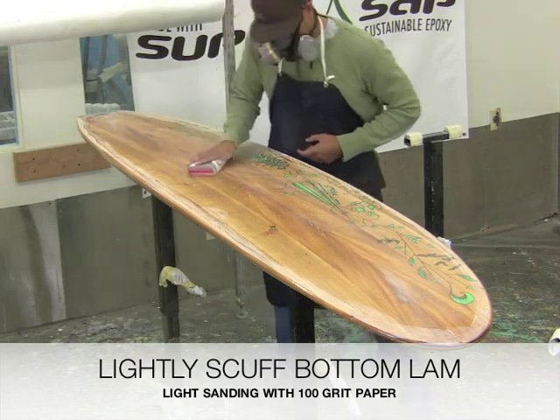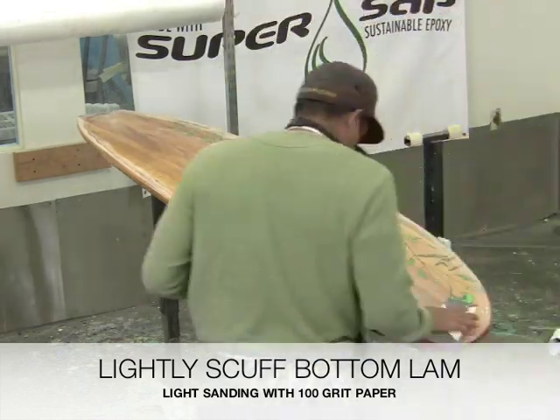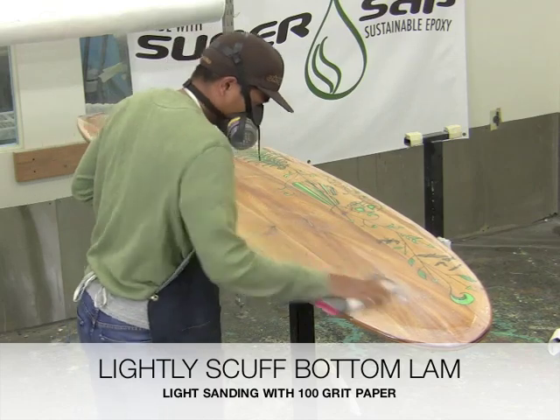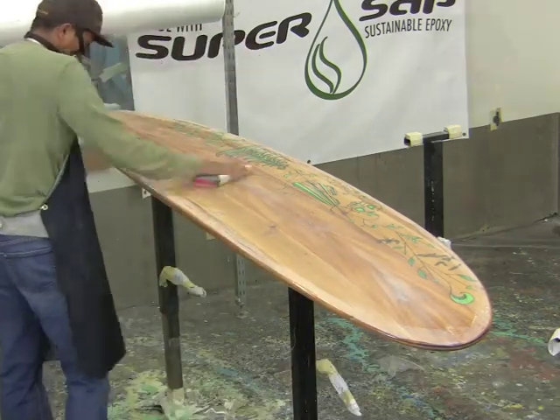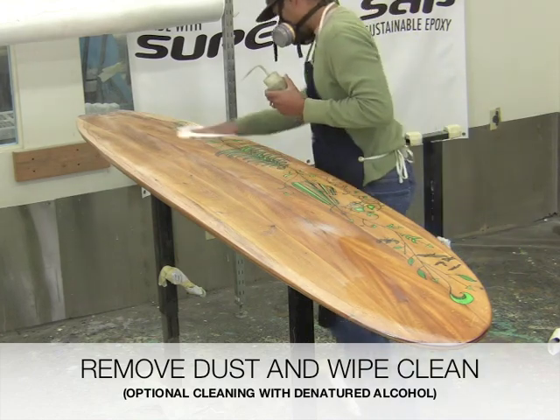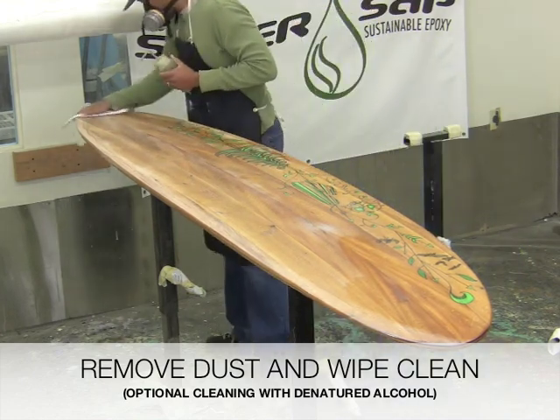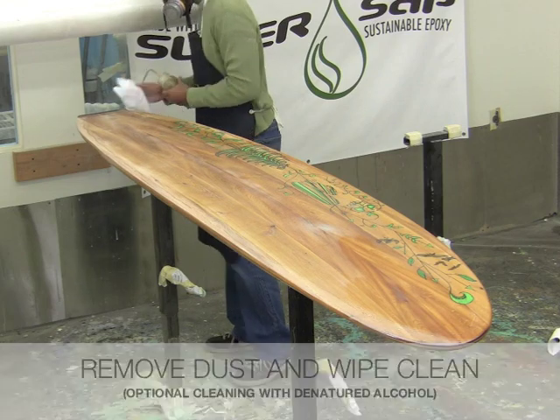Lightly scuff the cured bottom lamination with sandpaper so as to create a mechanical bonding surface for your hot coat. Then remove any residual sanding dust with a clean dry brush or wipe down with a clean rag and some denatured alcohol.